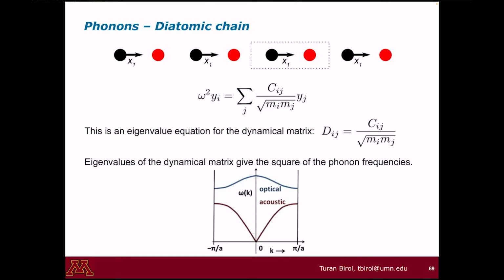Okay, yeah, thank you. And the conceptual difference between these two matrices, apart from these factors, is that when we say dynamical matrix, we are talking about some dynamics. So there should be both forces as well as the masses in there. This is why D is called the dynamical matrix. C is a force constants matrix. It's just a second derivative of energy. C doesn't know anything about the masses of the atoms, so C cannot give you the frequencies themselves. It only tells us how large the forces on the atoms are.